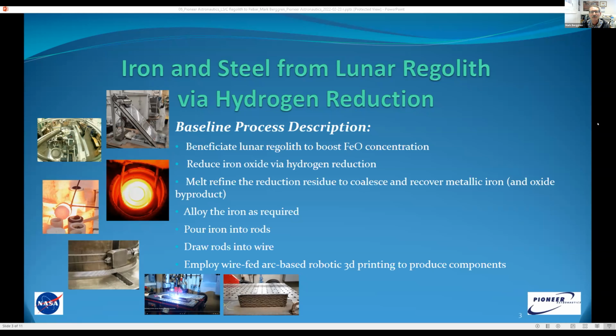And so just briefly, what those operations are initially would be to beneficiate lunar regolith to boost the iron oxide concentration, whether that's from ilmenite in rich form in mare soils, relatively speaking, or even in highlands type soils, or with some prospecting and care and attention, finding those anomalous high FeO regions near the South Pole, closer to Artemis operations. By the way, the photos show some of those methods. So the beneficiation would be particle size separations, magnetic and electrostatic separations.